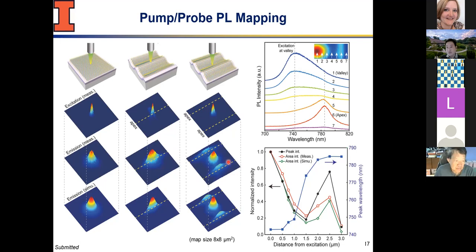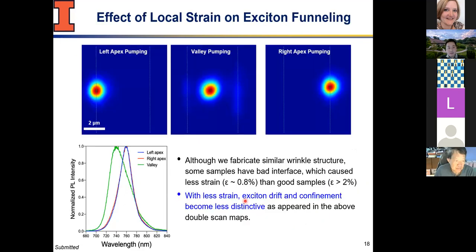And if there's no drift, that's what you don't see there. And then this is our model prediction based on the equation I showed you. You can study more and be more quantitative with the spectrum, with the model. And it turns out it fits very well. I think I can only say that with our simulation, the model versus the measurement.